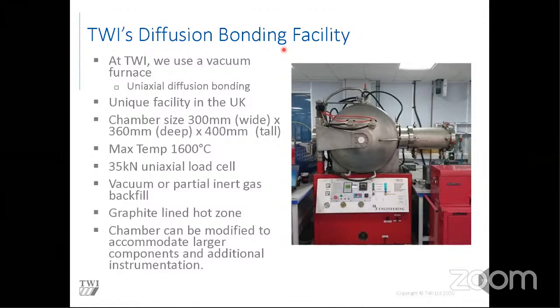The working zone is 300 millimeters by 360 by 400. We can go up to 1,600 degrees Celsius, and the hydraulic ram going through the center can apply up to 35 kilonewtons of load. This furnace is operated in a vacuum 99% of the time, but we can put a backfill of an inert gas in there if we need to.